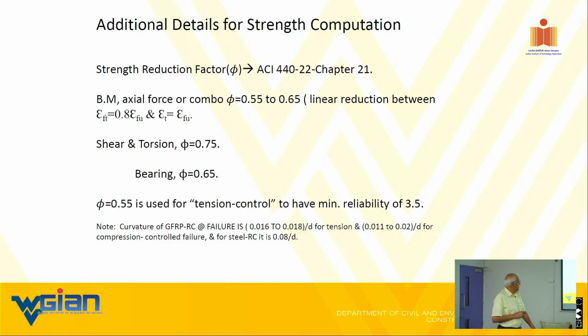If you remember, I told you the curvature of FRP, glass FRP based failure, we have found after 20 to 30 tests, 0.016, I already told you, in this range. For tension, 0.11 to 2 divided by D. For compression control, you can see what it is for steel. So again, remember, we want the curvature to be as close as possible to steel, but that's not coming out. And this helped in terms of energy absorption. That is where our compression control design is coming into play.